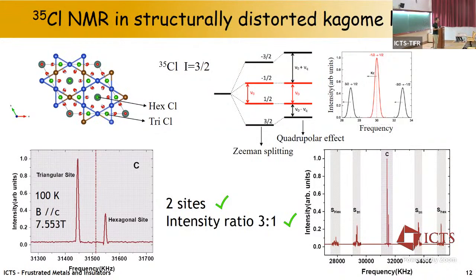Chlorine is spin three-halves, so it is quadrupolar active. It has a quadrupole moment, and it's sensitive to the electrostatic environment. So we expect not one line for one chlorine site, but actually three: one central line plus two satellites. And indeed, we do see, so this is the central line that is here. This is a zoom of this central line. And on each side, you have two pairs of satellites corresponding to the two sites. So that's textbook. That's what we expect.